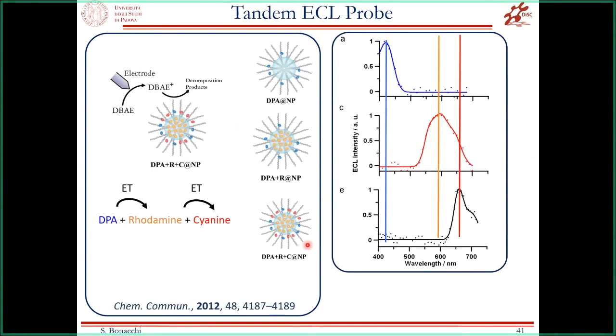And we use the same kind of approach to obtain an energy transfer ECL probe. In this case, we use the same kind of structure, and we dope it with three different kinds of ECL active probe, diphenylanthracene, rhodamine, and cyanine, in order again to have a highly efficient energy transfer among these different dyes, from the blue emitting one through the red emitting one, the cyanine. We use the same kind of ECL approach to tune the emission in the ECL probe mode. And so we control the final color of emission by means of ECL, so again without use of excitation.